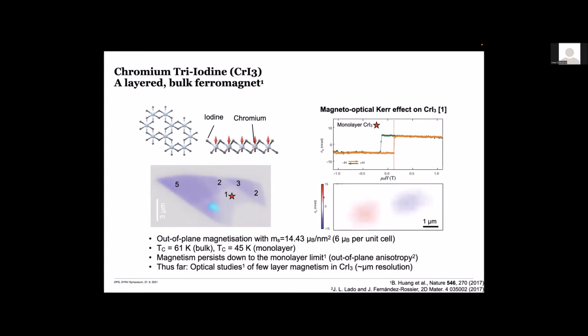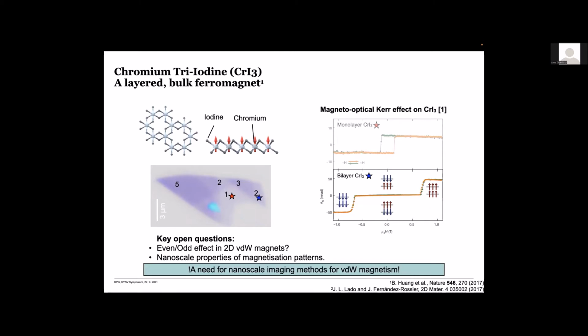Now, one big question that came about already with these very first studies of chromium triiodide has to do with the layer dependence of magnetization in these materials. Namely, it was shown, and you see the data over here, that for chromium triiodide, one could see an even-odd effect in the sense that odd numbers of layers showed the typical hysteresis curve that you would expect for a ferromagnetic sample, whereas even layers of these materials did not, and in fact showed no remnant magnetization here. So you can of course readily explain that just by postulating that adjacent layers show an antiferromagnetic interlayer coupling.